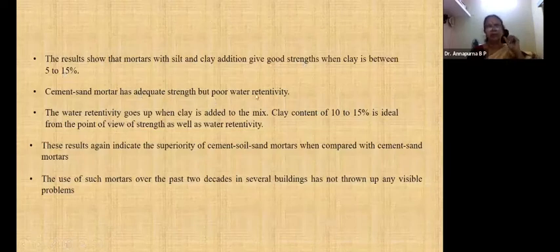Cement sand mortar has adequate strength but poor water retentivity. This is cement sand mortar, it's not soil, and it has poor retentivity. The water retention goes up when clay is added to the mix. Clay content of 10 to 15% is ideal from the point of view of strength as well as water retentivity. These results again indicate the superiority of cement soil sand mortars when compared with cement sand mortars. The use of such mortars in the past 2 decades in several buildings has not thrown up any visible problems.